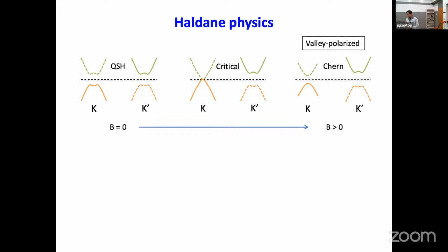So then you have an interesting scenario. Let's say that we tune our electric field to make the gap very small. Let's say that just immediately after band inversion we have a small gap quantum spin Hall insulator. Then we apply a small magnetic field to the system. One valley will acquire positive Zeeman energy, and the other valley will acquire negative Zeeman energy. So we enlarge the gap at the K prime and make the gap at the K smaller, until they invert after a critical magnetic field. After this band inversion, the band at one valley becomes topologically trivial, while the other band still remains topologically non-trivial. Okay, they still have a Chern band at the K prime valley, but they are not a Chern band at the K valley anymore.